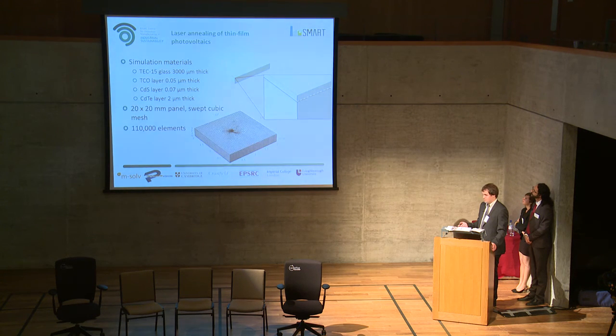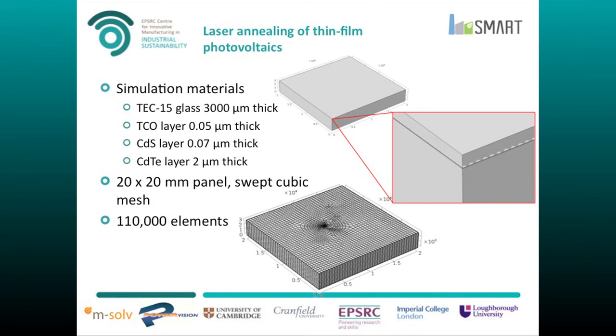To give you an idea of the scale of how thin this is, that's the whole panel. And then if we zoom in to a picture less than a pixel thick there, we can see the cadmium telluride layer and then the very, very thin other layers. We then create a mesh, which looks like that, which has 110,000 elements covering all of the layers. It's a 20 by 20 millimeter panel, so it's quite a lot smaller than the physical ones, but that's purely to reduce computing time and actually hopefully complete the simulation before everybody dies of old age.